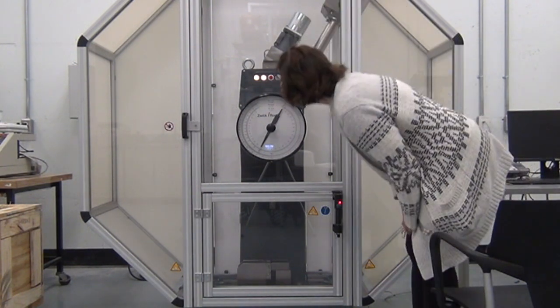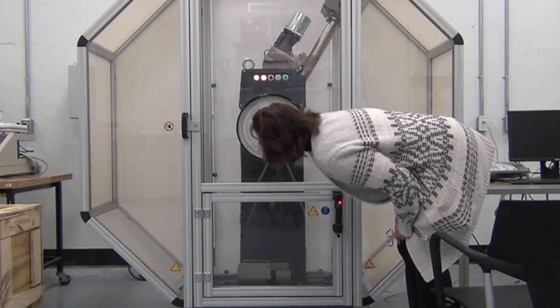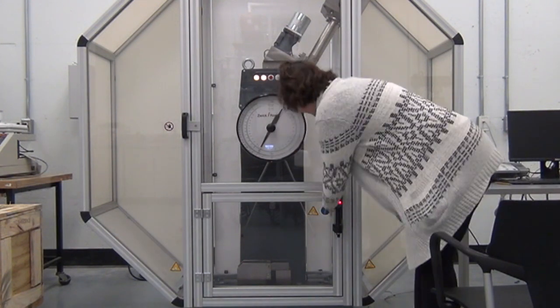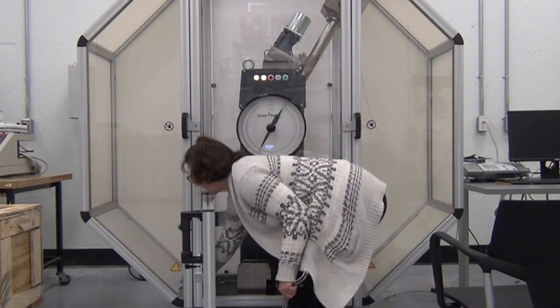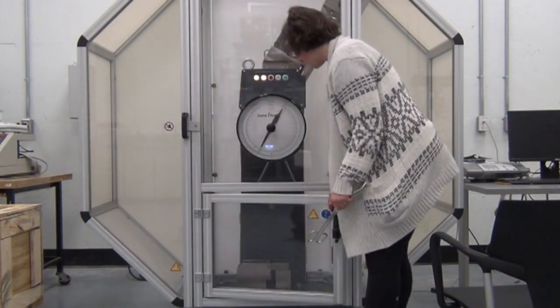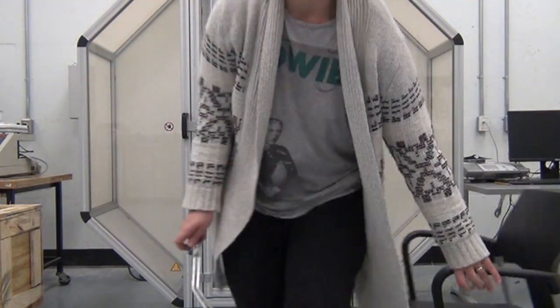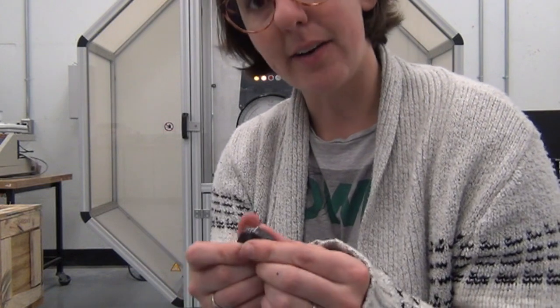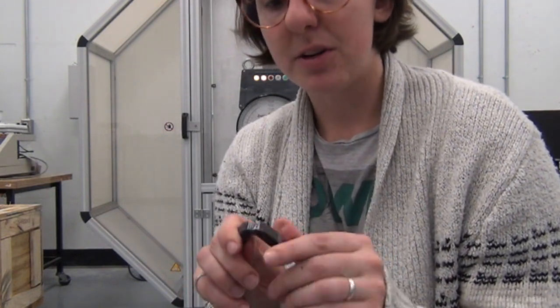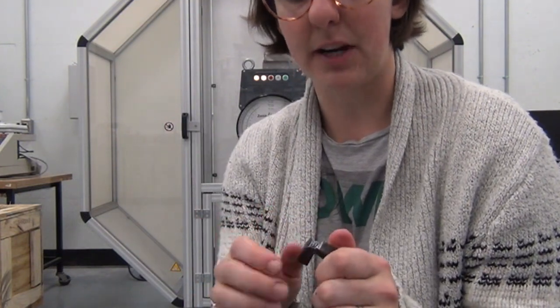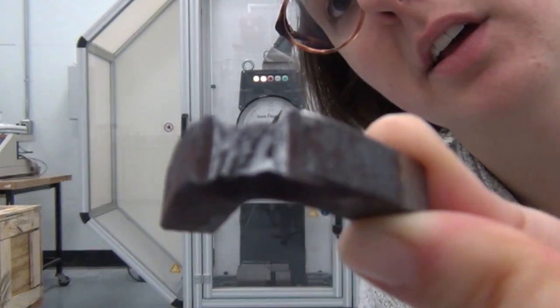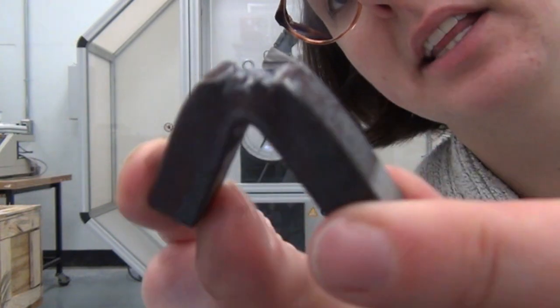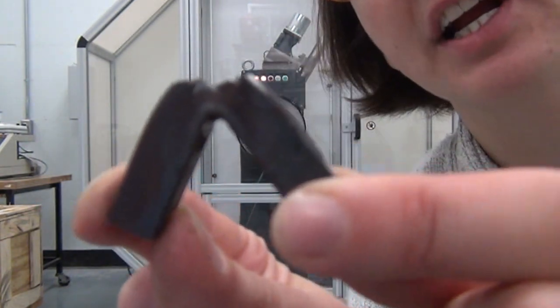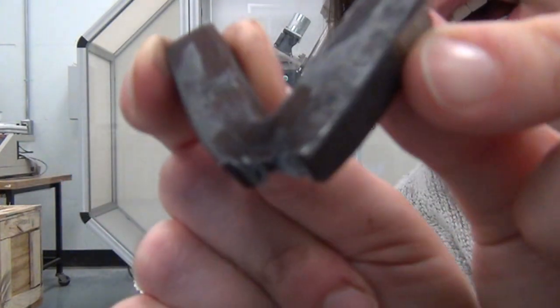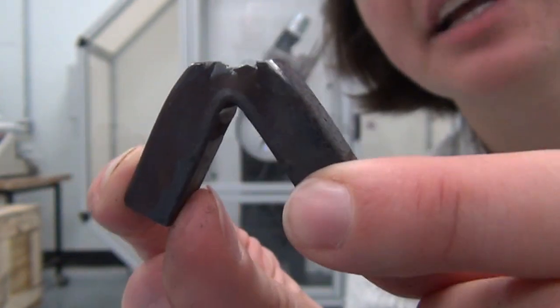So the test is complete now. Looking at the dial, I can see an impact toughness of 140 joules, and I can retrieve my sample so that we can look at the fracture surface. One thing I'll tell you right off the top is that my sample was room temperature going in, and now it's quite warm. So it's absorbed a lot of energy, and there's been a temperature change in the material. If we look closely, we can see that we have what appears to be a pretty ductile fracture here. So you can see that the sample is still intact.